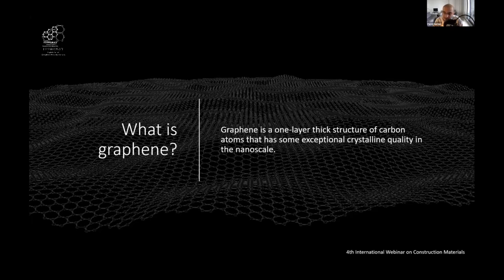Now, this high thermal conductivity of graphene particles help in cooling down the inner parts of the concrete blocks, especially in the first 3 days when the strength gain occurs. Once the internal heat finds its way outside of the concrete block, the chances of cracking reduces by a lot. In fact, in the traditional curing processes, we spray water on the surface to cool down the block. Relevant literature had reported up to 30% improvement in the compressive strength of concrete reinforced with graphene particles due to the better internal curing process.